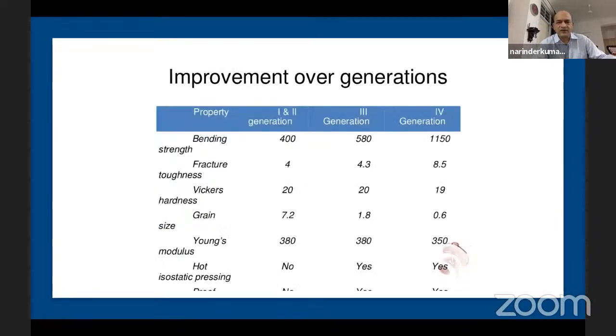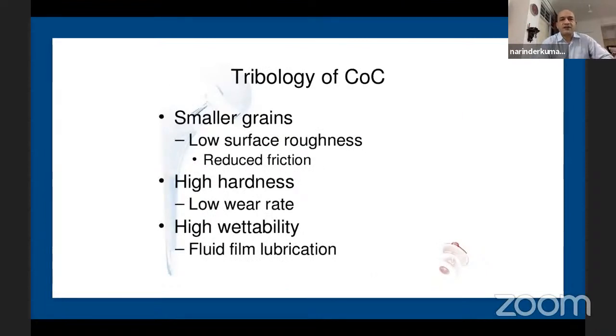These improvements are fairly technical; if somebody wants details they can ask for my presentation and I'll send it over. But one must understand the tribology of ceramic-on-ceramic: smaller grains have led to lower surface roughness, leading to reduced friction. High hardness of delta ceramic has led to low wear rates, and high wettability has led to fluid film lubrication. In fact, ceramic-on-ceramic is the only bearing combination in which fluid film lubrication happens - most others are either boundary lubrication or mixed.